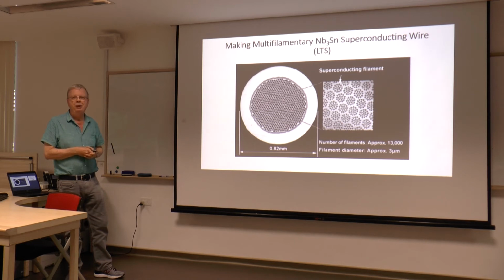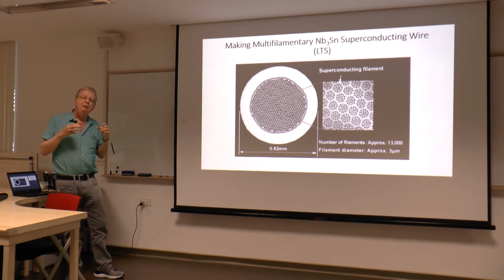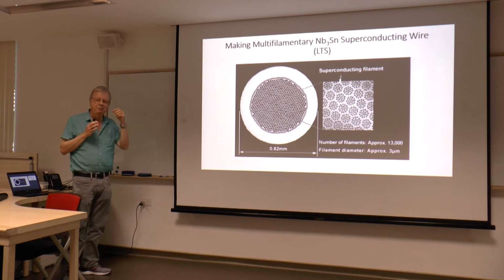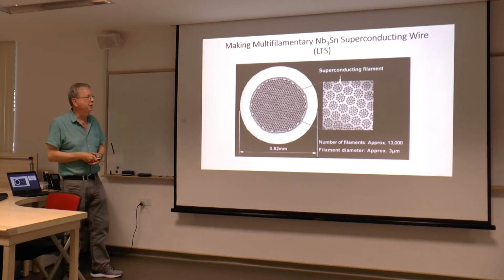You don't allow the wire to be brittle until it's already in its final form. And then there's one further trick. If you do it right, you can put the wire under a little bit of stress when it cools, and TC goes up a little bit. So people are in there getting every 1/10 of a degree and every Tesla out of the critical field that they can. So there's a lot of tricks, some of which are proprietary.